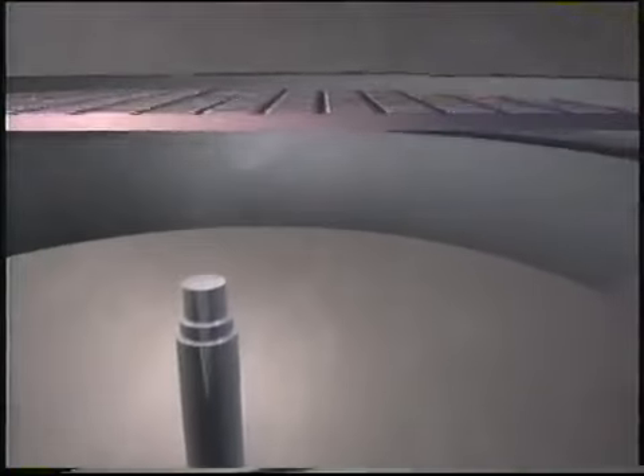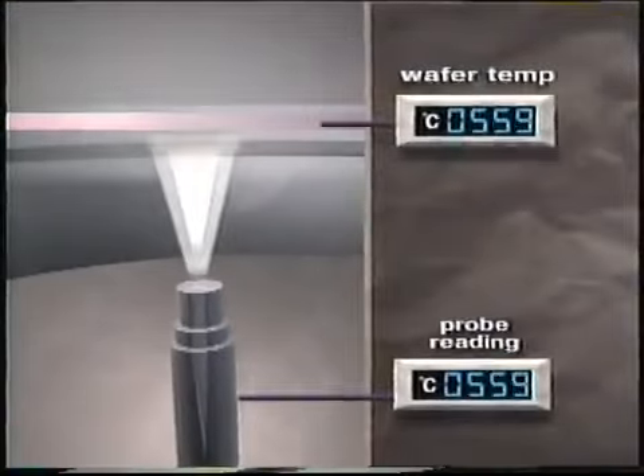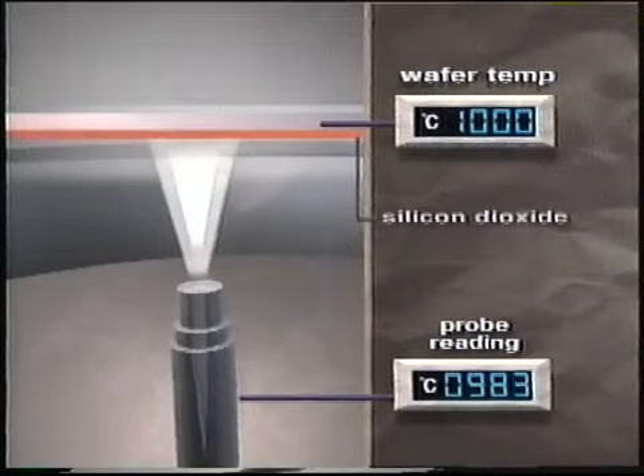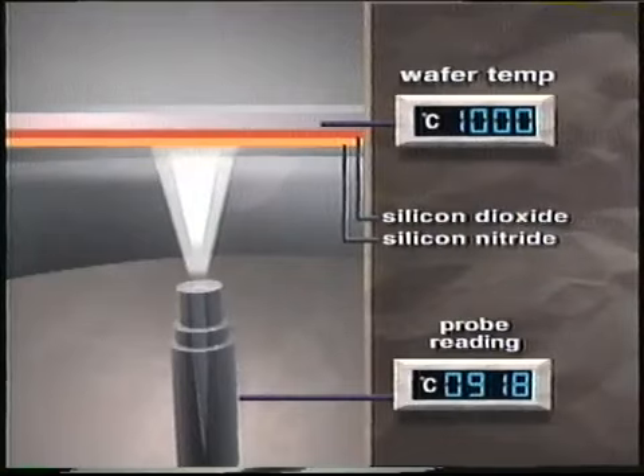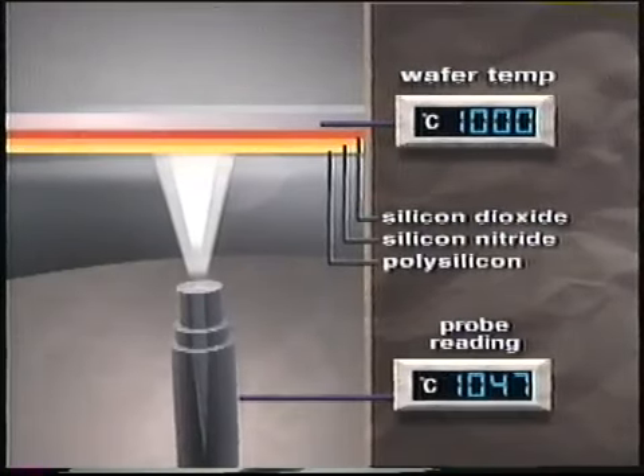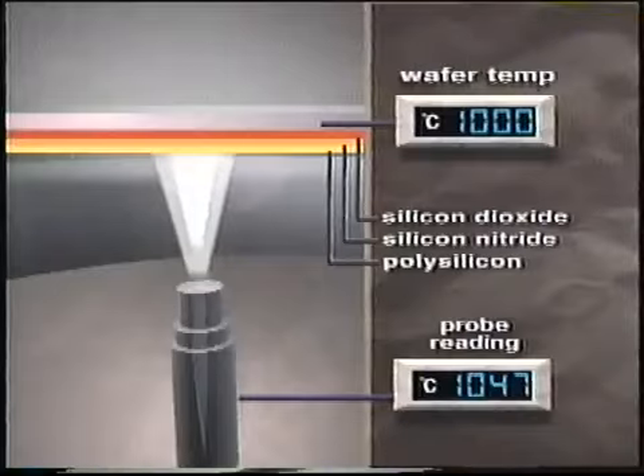A second problem with conventional optical pyrometers is that they fail to adjust for the variation in the backside emissivity of the wafer. Maintaining temperature control from wafer to wafer requires backside etching of the films, or a measurement of the emissivity and an adjustment to the production process.